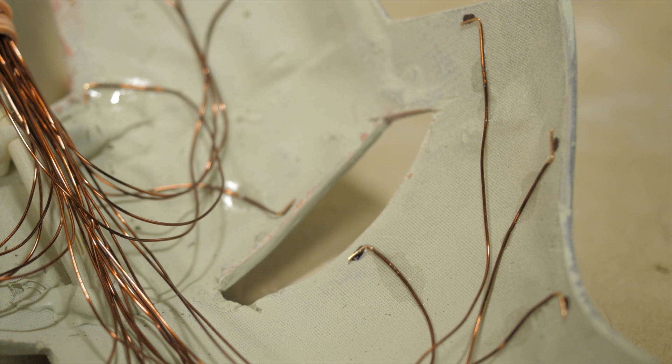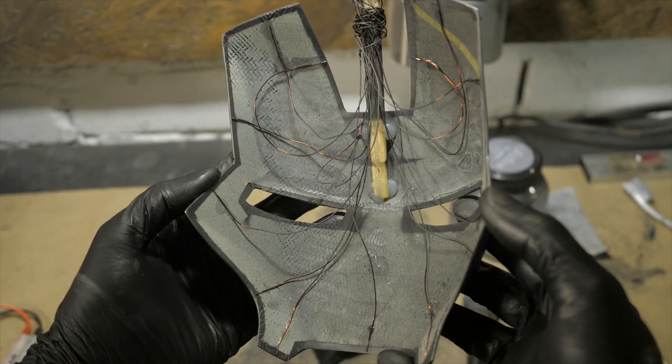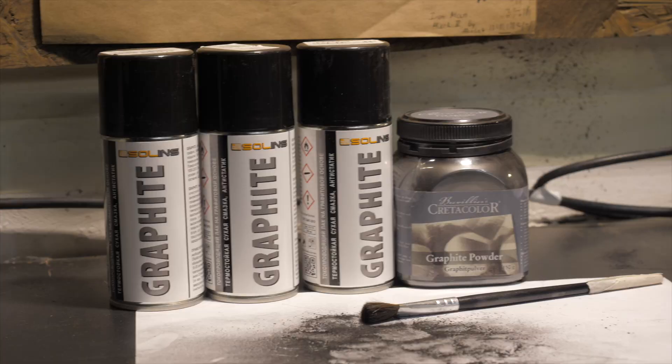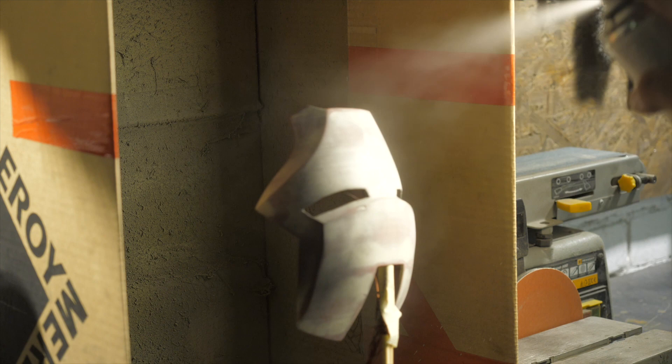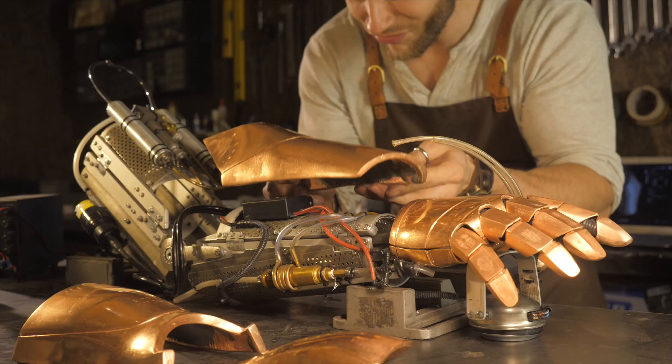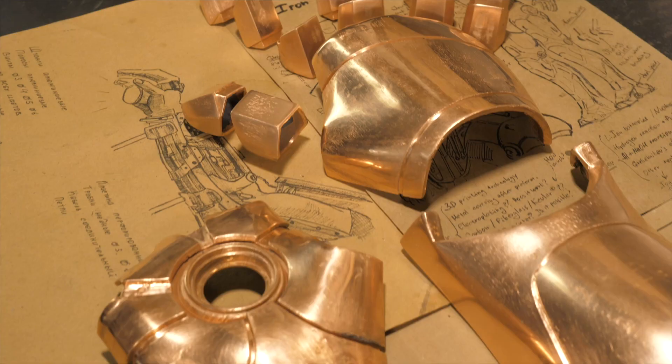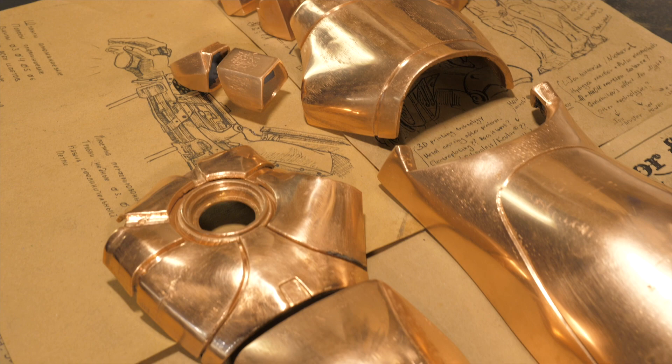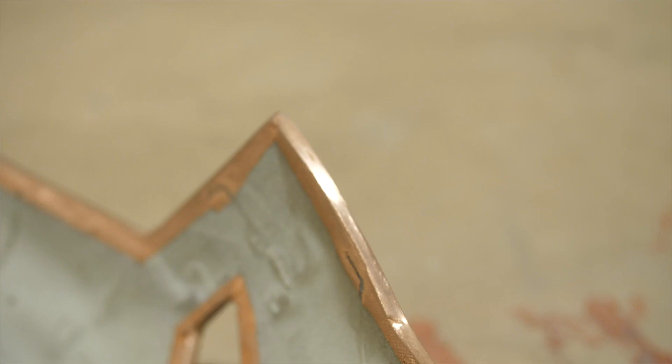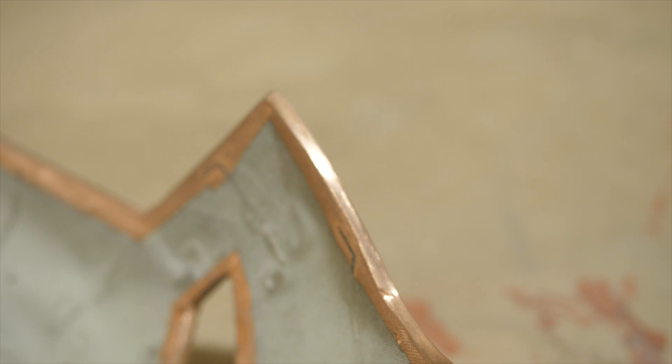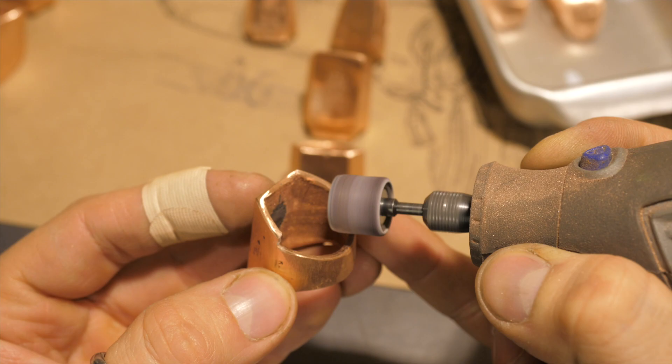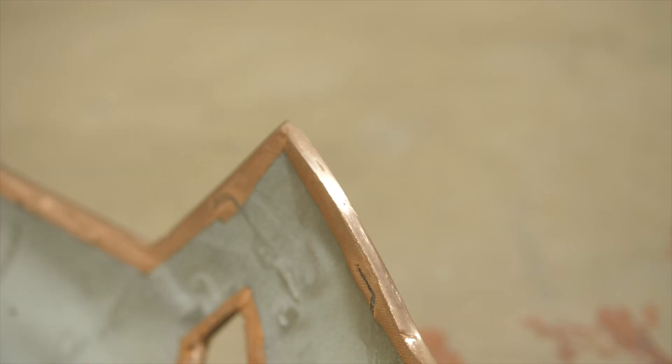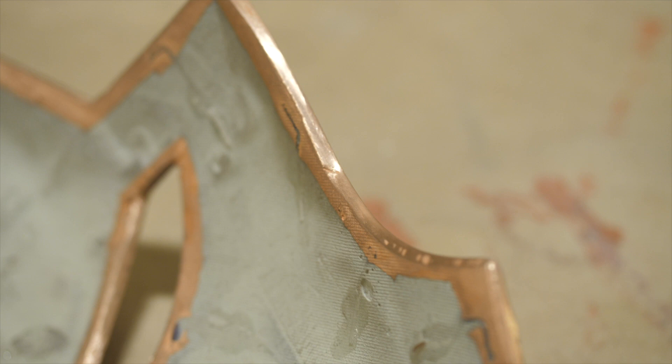After attaching a lot of contacts, we proceed to create an electrically conductive layer. For decorative use it would be enough to cover only the front side of the part. But since we are working on functional parts that will be stressed and friction against other parts, it is better that the copper coating is not only on the front side, but also on the side ends and a little more on the inside. Then the copper layer will not peel off the ends and, in addition, will close the edges of the plastic part and the composite as a protective shell.